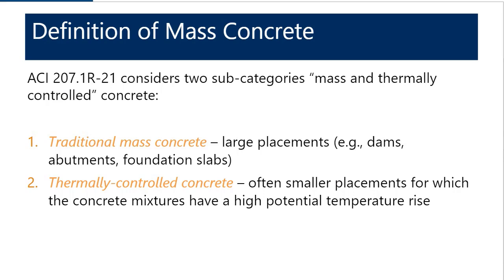The first category is traditional mass concrete. So these are large placements that many of you probably think of when you think of mass concrete. Things like dams, abutments, foundations, slabs, very large elements where the thickness is going to govern the temperatures that are generated. But there's also this newer category that they've talked about called thermally controlled concrete.